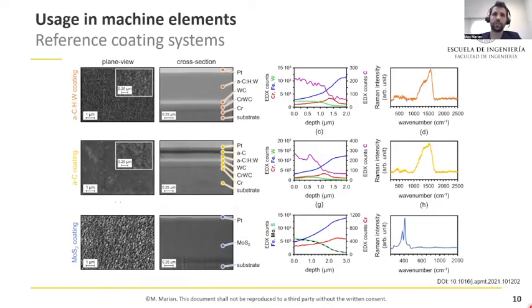Because a comparison only with uncoated bearings is not overly meaningful, because no one would actually operate the bearing in such a way, we wanted to compare the MXenes also to other more established solid lubricant coatings produced by large-scale deposition processes. So here we can see images of the surface and in the FIB cross sections, some EDX line scans and Raman signals of three studied reference systems.